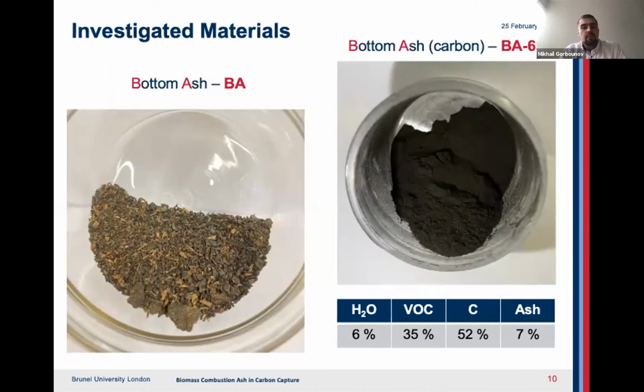Generally, BA consists of three main constituents: the unburned biomass, the ash itself, and the unburned carbon. Therefore, we have aimed to extract the carbon, and the resulting material is pictured on the right there, which was denoted as BA-6. And we can report that the extraction process yields good results, as the ash impurities sum up to just under 7%, and the moisture content is around 6%, with the rest being volatile organic compounds and fixed carbon.